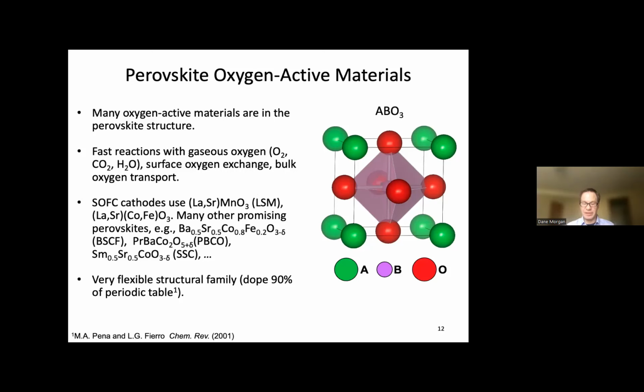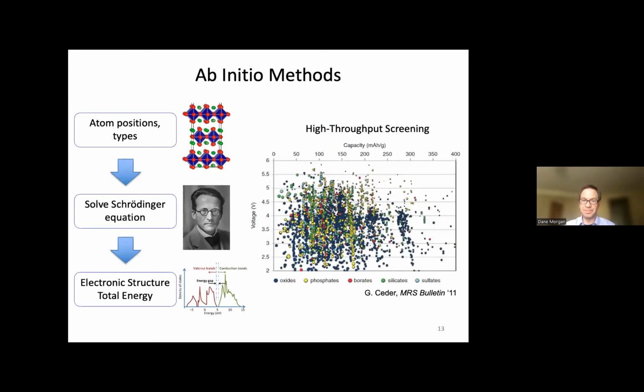And actually, somebody once did a study of perovskites and found that you can dope into this structure, meaning you can put atoms into the A site or the B site that make up 90% of the periodic table. You can put some anions on the oxygen site as well. It's just an incredibly flexible structure. So there's really a huge space of possible perovskites one might consider. And so one of the challenges we saw is, could we use computational tools to help us work through that very large space of possible materials to target the most promising ones for further experimental study?